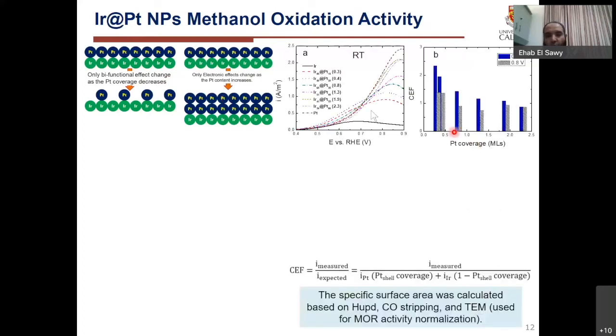As a reminder, when we go from submonolayer to monolayer, we are decreasing the bifunctional effect but maintaining the electronic effect. If we just add more layers, we are buffering the electronic effect and there is no strain effect. Because iridium and platinum both have some catalytic activity toward methanol oxidation, instead of just seeing how they react separately, we want to see how they enhance each other, the synergistic effect.